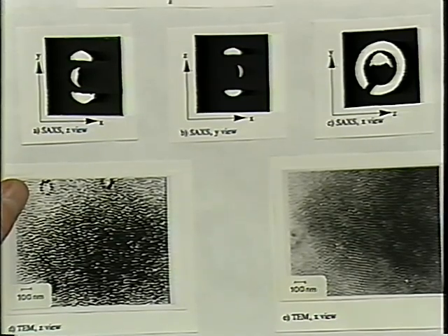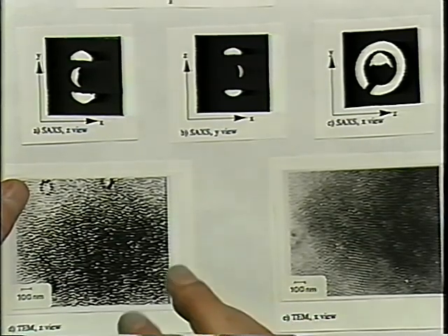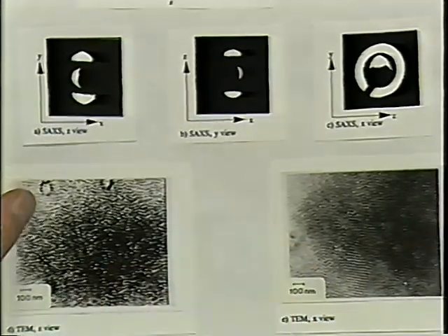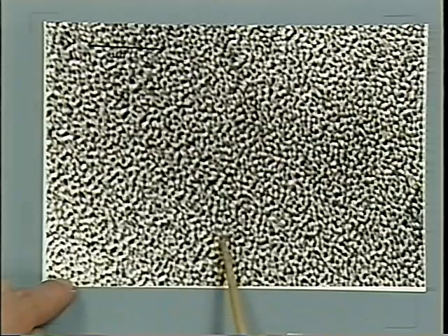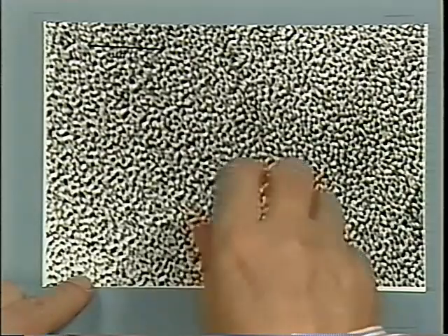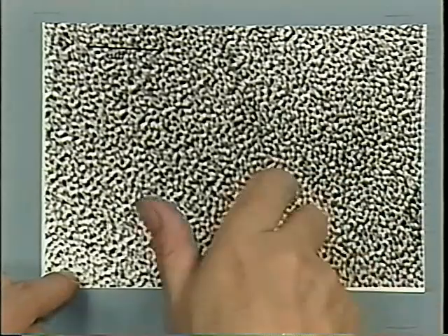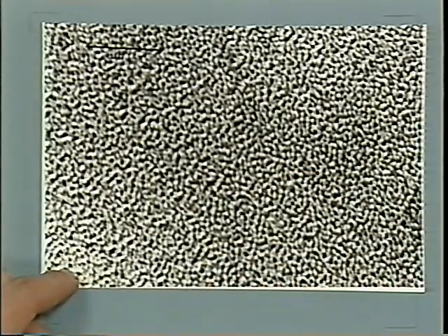It's not the self-organized system which you produce in some equilibrium thermodynamic experiment where you give time for formation of order. That's the morphology. Here's a larger picture of that type of morphology, and you can see that it's highly disordered. This is down the cylinders here, and it's hard to see any irregularity in the hexagon pattern because the cylinders are so small in this case.